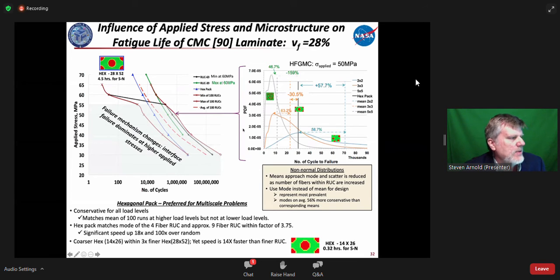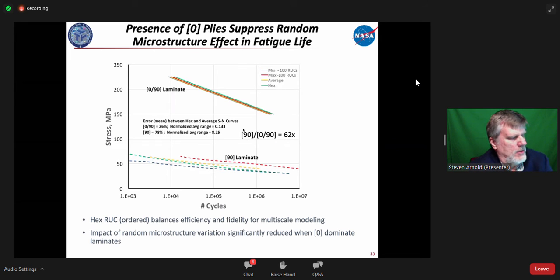And really tying in with this is this idea in the literature. Most people have done studies with microstructure on a 90 laminate only. Here we're looking at what the response is in a laminate situation. In particular, here is a 0/90, and you can see that the variation here is actually reduced quite significantly due to the presence of the zero ply, and in this case it's 62 times less variation in a 0/90 laminate. So that's something to really keep in mind from a practical standpoint, that more than likely, at least for laminates that are dominated by the zero ply, you're not going to have to worry too much about the microstructural details.